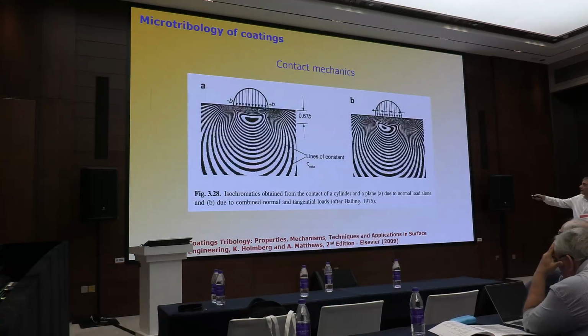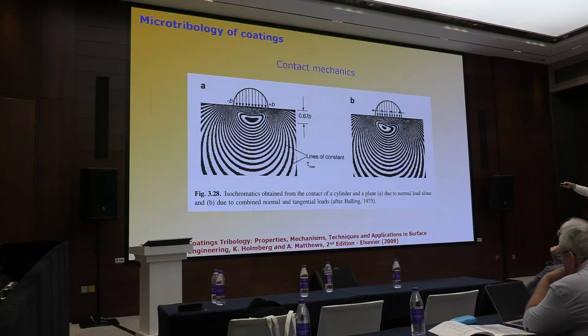Why? Because with this equation, when you apply a load, this is the one body and this is the other body. When you have a body on another body, you can analyze this field of pressures in the softer material. And when you apply a force, you have the highest shear stress inside the material, not at the surface. According to the Hertz equation, the shear stress maximum is in the material. This is very important because you can study, for example, the delamination of a coating or thin film. When you apply the force and the maximum reaches the interface of the coating with the material, the delamination starts. This is the idea of how to use this equation to understand the delamination of coatings.